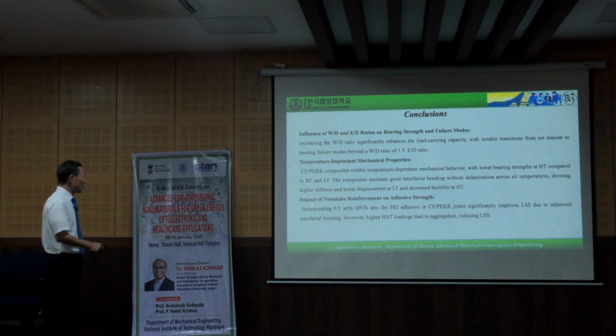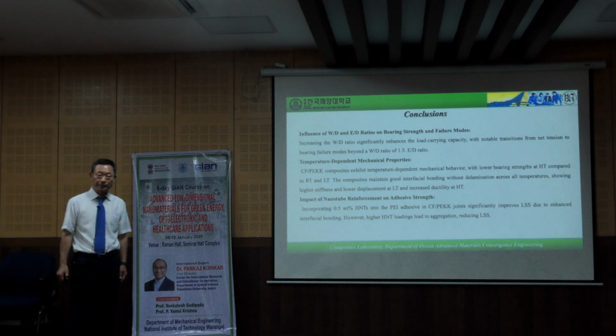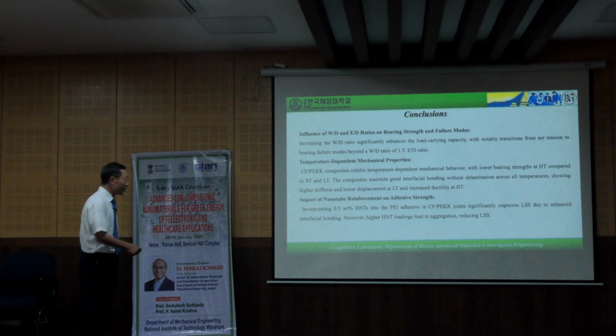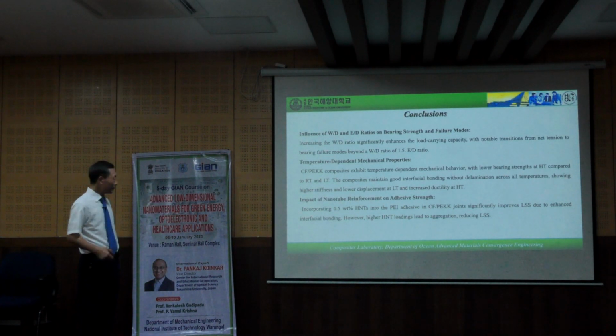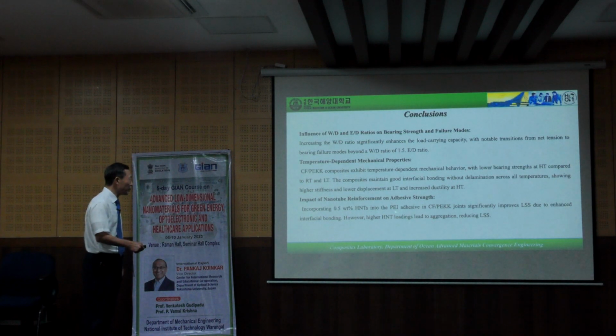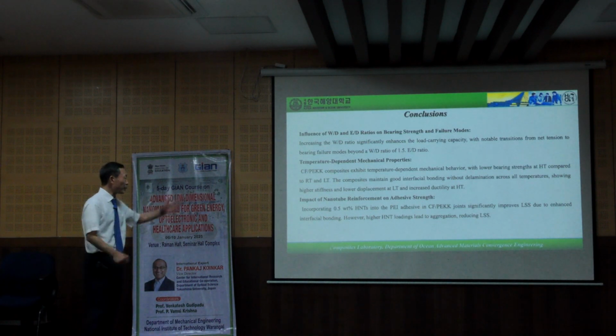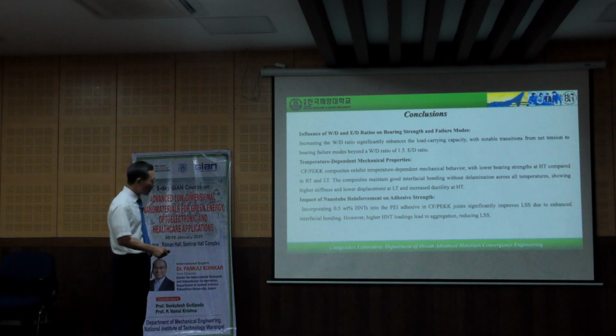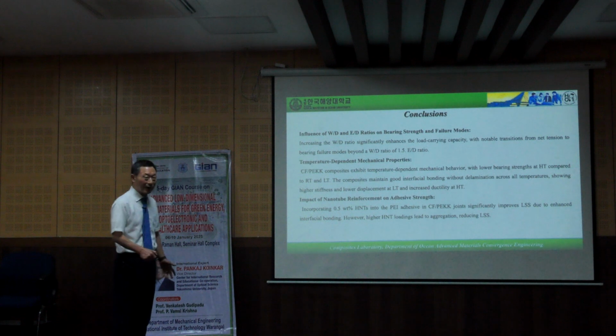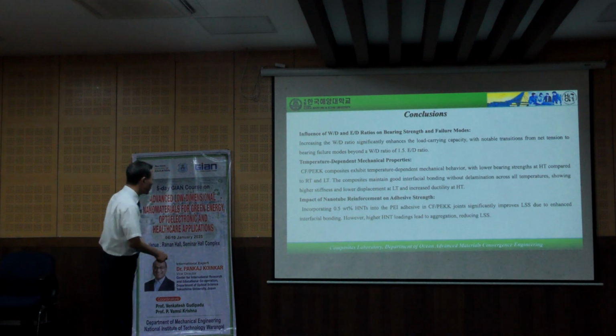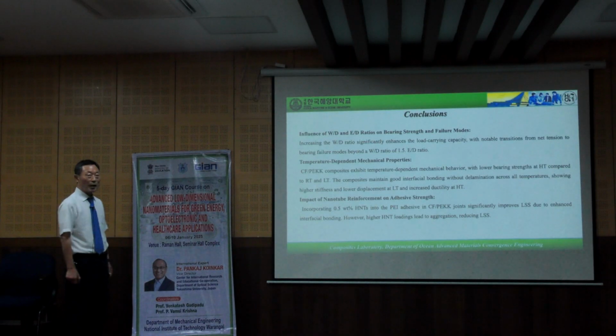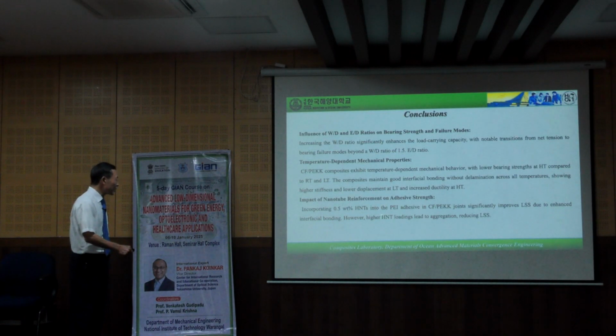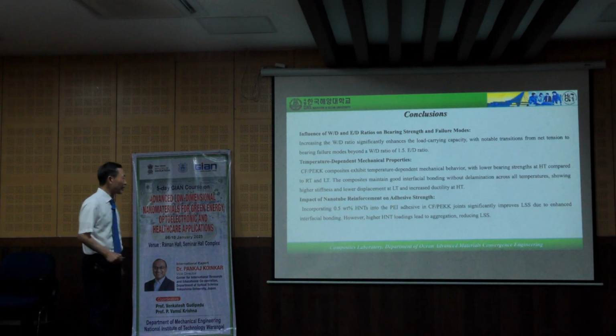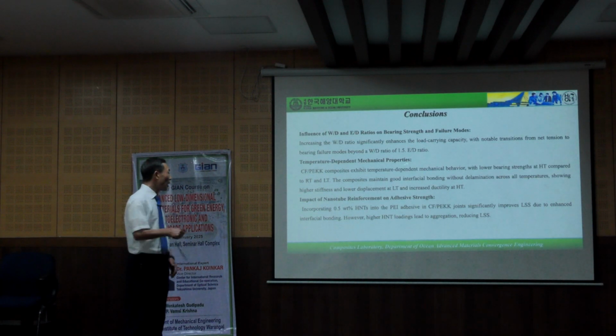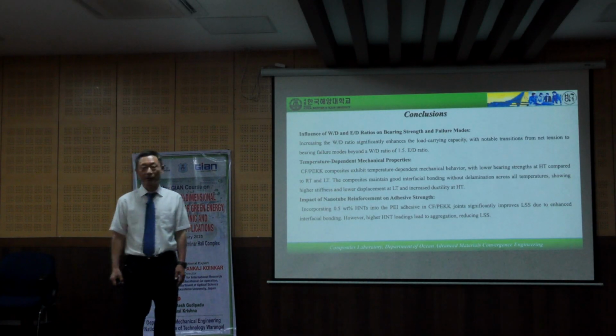And the third, impact of a nanotube reinforced on adhesive strength. Incorporating just 0.5 HNTs into the PEI adhesive in CF/PEEK joints significantly improved lap shear strength due to the enhanced interfacial bonding. However, higher HNT loadings lead to aggregation, reducing lap shear strength.